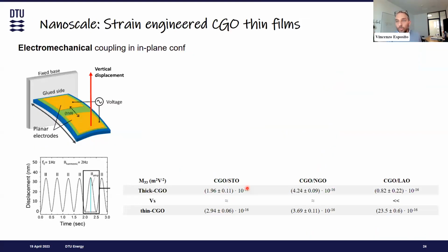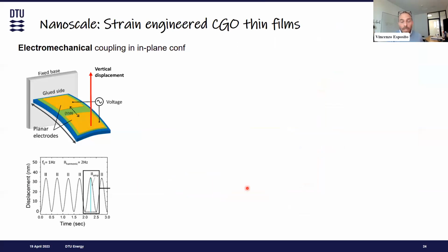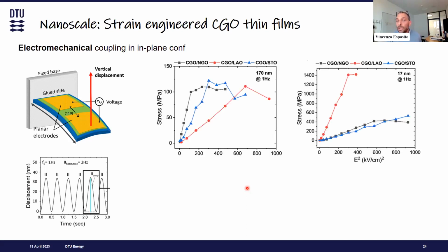So let's go to the results of this case, and what we notice is that if we do a cantilever like that, we get the second harmonic, which is typical of electrostriction. And then immediately we notice that the thick film and the thin film have similar properties when they are relaxed or in a tensile strain. We're talking about in-plane tensile strain. However, in the case of in-plane compressive strain, the electromechanical response is much higher.